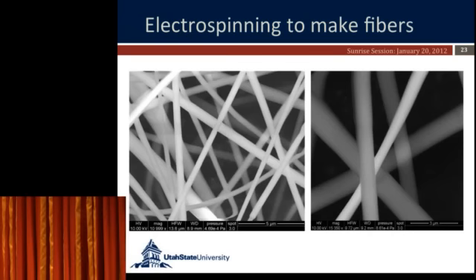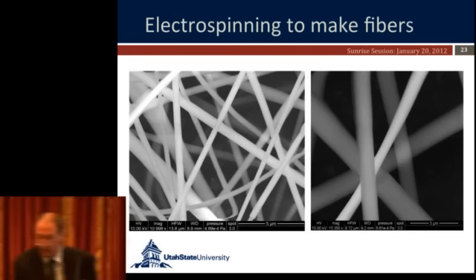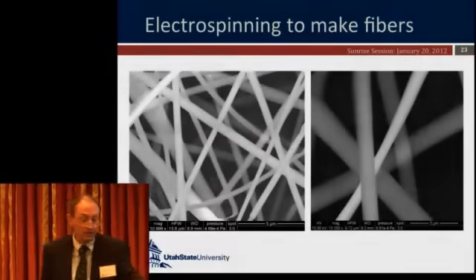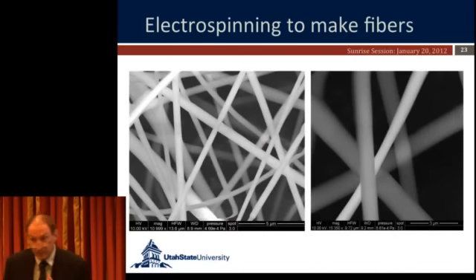So what he learned how to do was to do the same thing, except that he's able to make something that is in parallel, so that it looks more like this. So he ends up with a parallel fiber. Even though it's composed of lots of little teeny fibers, they're all parallel to make a yarn. And that's what you see some of here. So here's our 5-micron diameter right here, so that's the smallest we make. You can see that almost every fiber in there is way smaller than 5 microns. So we then tested them.